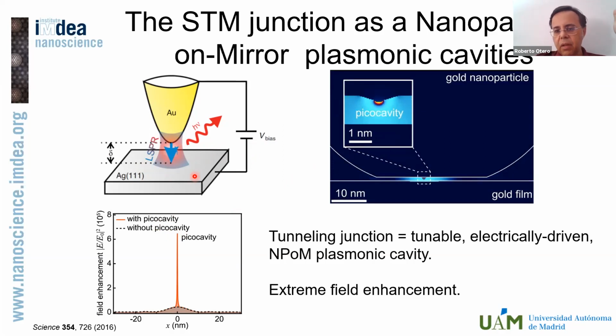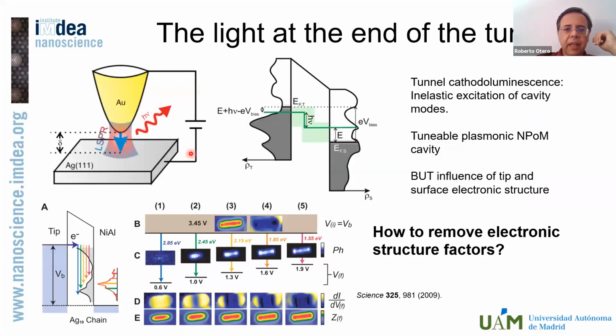And it has one important advantage, and it is that since this is an STM, we can modify both the distance between the tip and the sample with picometer resolution and the lateral position. So we can choose whether we stay on top of a single molecule, on top of a metallic sample, or anything like that, right? So all this would be very interesting if we really knew exactly what we were measuring when we measure luminescence induced by STM.